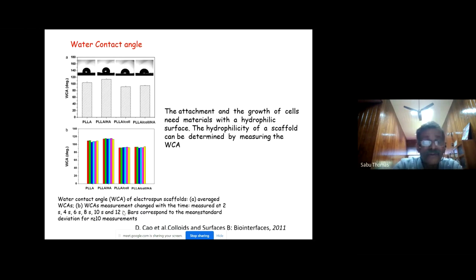Now I wanted to show you another interesting slide of Professor Cao. Professor Cao made use of PLLA. This is a PLLA scaffold, and the contact angle of the PLLA scaffold is pretty high. PLLA is hydrophobic. But if you mix with hydroxyapatite or collagen, or PLLA collagen hydroxyapatite, you see the hydrophobicity could be reduced. The system becomes more hydrophilic. So this is also quite interesting. For tissue engineering applications, we need more hydrophilicity.